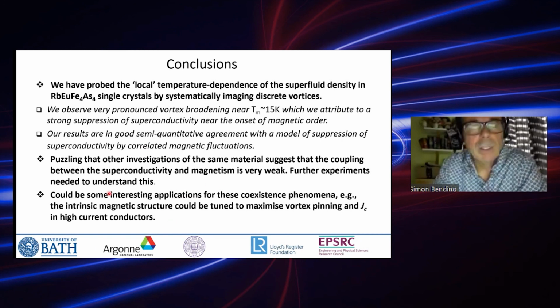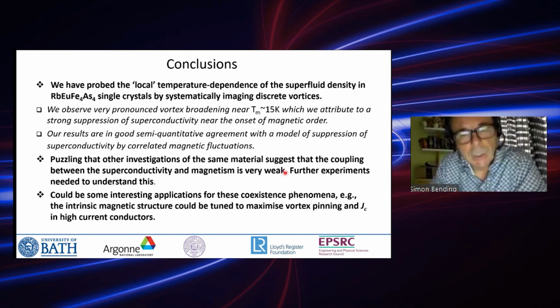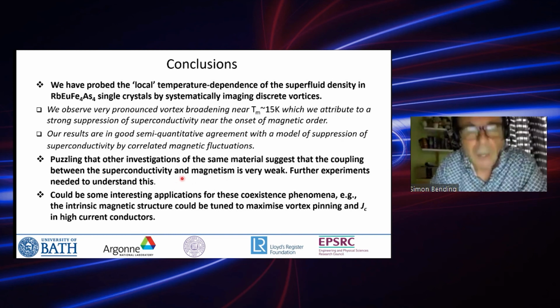There are still, I think, a lot of open questions. It's puzzling that the other investigations of the same material that I showed you suggest that the coupling is weak or sometimes non-existent. But I think that probably reflects how complicated this system is. So we have multiple superconducting bands. Each has a different superconducting gap. Each band contributes a different amount to the superfluid density, and each band will actually interact with a different strength with the europium moment. So probably different experiments are investigating different aspects of this complex problem. So we maybe shouldn't be surprised that they are not always obviously consistent with one another.